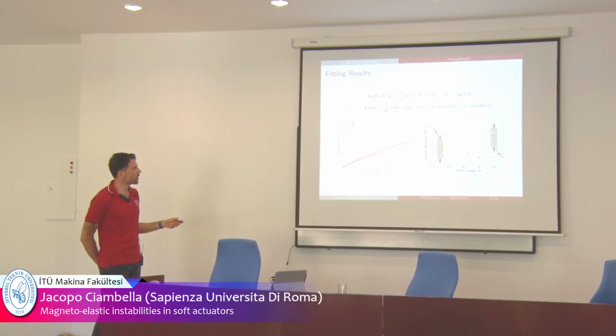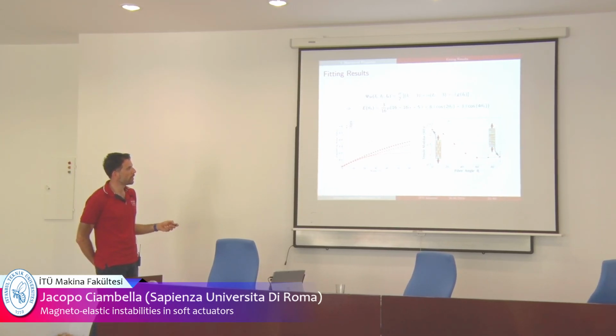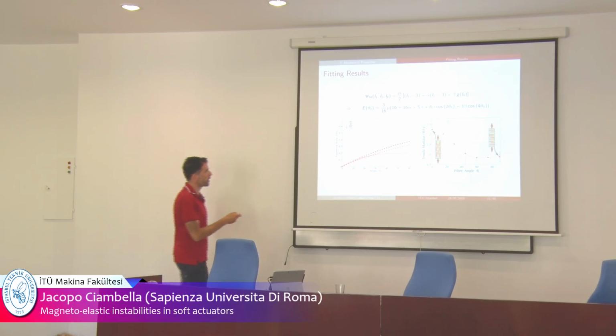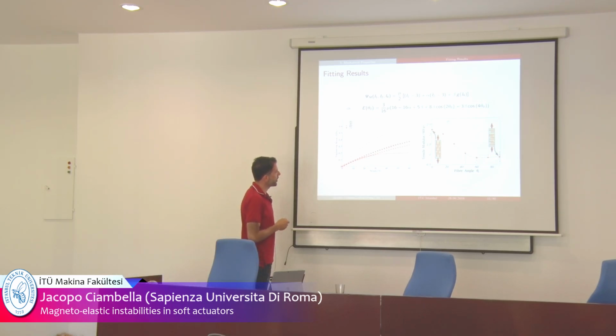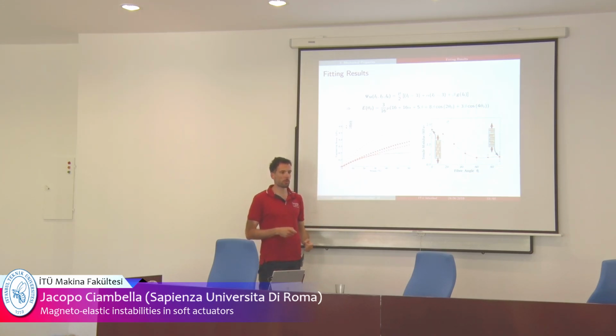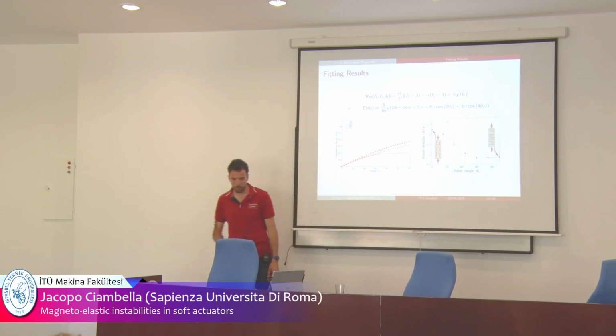And in fact, these are the results in terms of this model here. So it fits well the behavior up to 30% of strain, and then starts to diverge. But for our scope, 30% was more than enough. Okay, I will show you why. And this is the behavior of the tensile modulus compared to the fiber angle. Okay? These are the experimental results. So it worked pretty well. Okay?